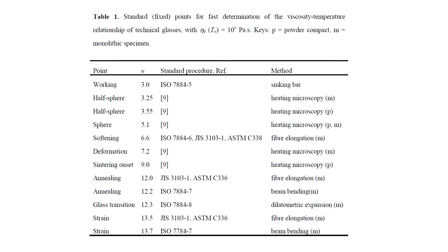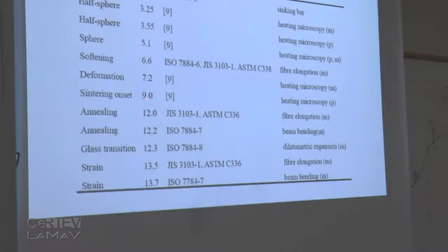You have a glass powder, you can bring this glass powder to a heating microscope. We have one here at LaMaV. And see when these particles start to sinter. The sintering onset viscosity is about 10 to the 9 Pascal second.